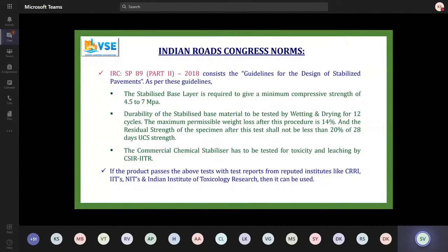Maximum permissible weight loss after this procedure is 14%. Residual strength of the specimen after this test shall not be less than 20% of 28 days UCS. A commercial chemical stabilizer has to be tested for toxicity and leaching by CSIR, IITR Lucknow, which we have already done. And if the product passes the above tests with reputed institutes like CRRI, IITs, NITs, Indian Institute of Toxicology, then it can be used.